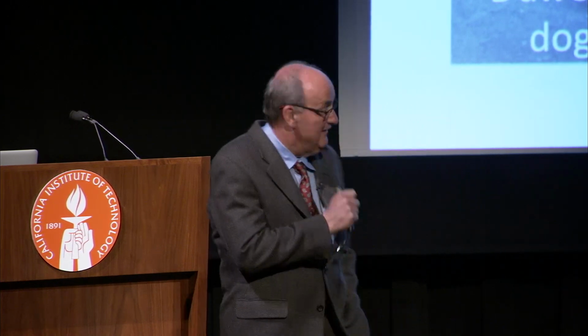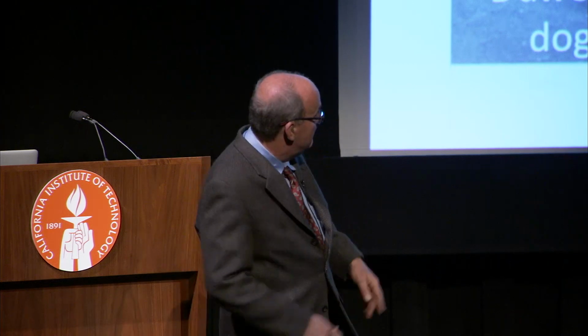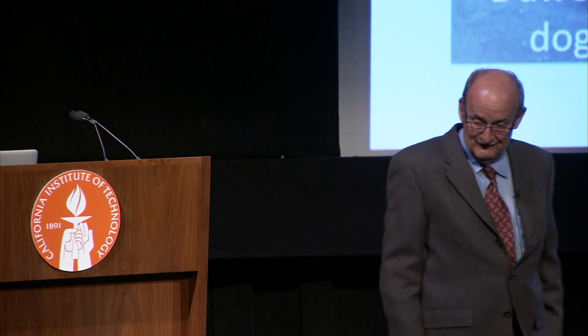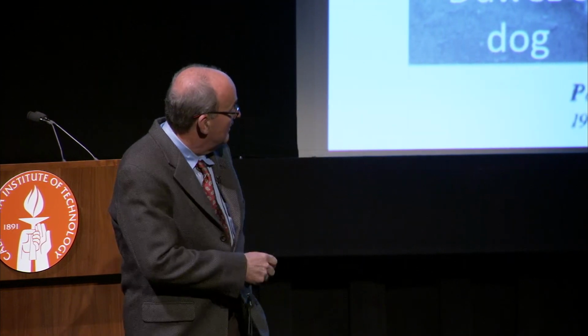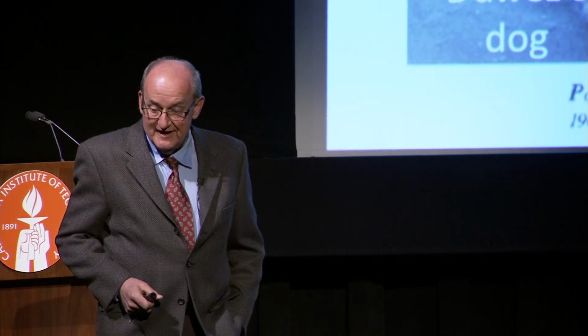You cool it fast enough, there are no crystals, you get a glass. That was the first metallic glass, 1959. Okay? Rapid solidification. Pol Duwez started a whole field. It was called rapid solidification technology for processing metals at high cooling rates. Right? But he discovered metallic glass. That first metallic glass was an alloy of gold and silicon. It's a gold glass. It's like 20 karat gold, but it's glassy.